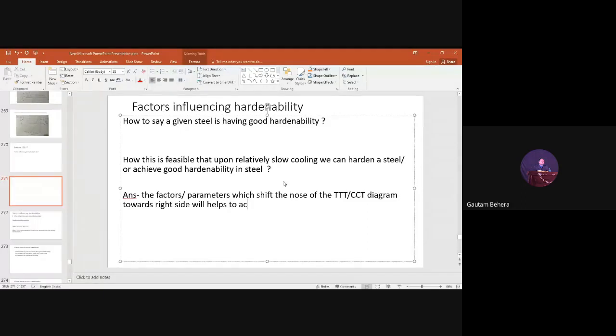Helps to achieve good hardenability, right? So if you want good hardenability characteristics in your steel, then there are certain factors which shift the nose of the CCT curve or TTT curve towards the right side, and that will help you achieve good hardenability. It simply means, obviously, adding alloying elements. Except cobalt, other alloying elements shift the nose of the C curve of the TTT or CCT diagram, right? So even if we are cooling the steel at a slow rate, we can achieve good hardenability.